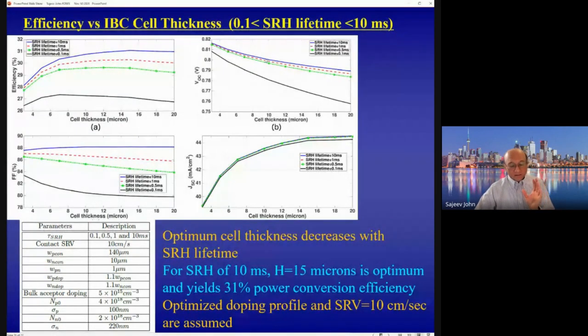And again, we use some realistic but state-of-the-art numbers for the quality of silicon as described by the Shockley-Read-Hall lifetime, which we take ranging between 10 milliseconds, which would be the highest quality silicon, down to 0.1 milliseconds, which would actually correspond to a type of good quality polycrystalline silicon. And we show that, first of all, in the case of the highest quality silicon with 10 millisecond lifetime, that's the blue curve on top, the efficiency increases with the thickness, but then reaches its maximum at 15 microns thickness and then starts to go down again. And that's close to 31% efficiency.